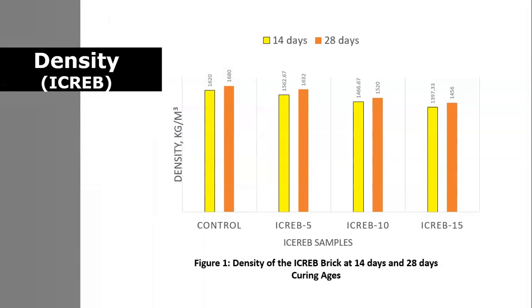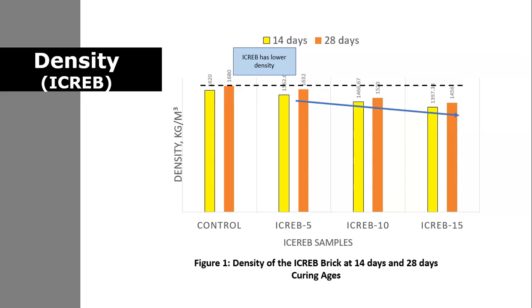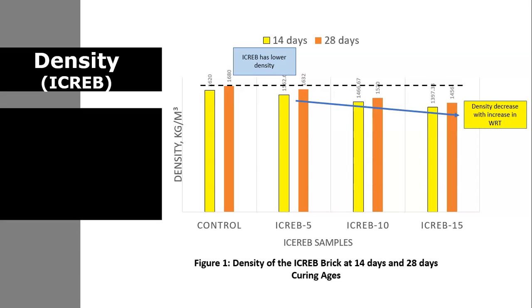Okay, the density of the ICREB brick is shown in Figure 1. With the addition of the waste rubber tire, it can be seen that the density of the brick sample is reduced compared to the control ICEB sample. It was also noted that as the replacement percentage increased, the densities of the specimens decreased. So there is an inverse relation that can be seen between the amount of rubber replaced and the densities of the specimens. The reason for this is possibly the low specific gravity of the rubber particles, which is around 0.9, compared to the specific gravity of the clay soil, which is more than 2.6.